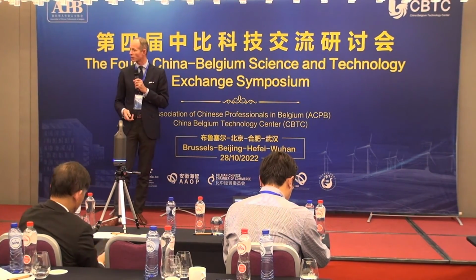Depending on the concentration of CO2, it will increase the process or not. And actually, this is identified as a drawback of concrete, because if the front of carbonation is going too close to the steel reinforcement, you will have a problem. But at the end of the day, this carbonation on all existing concrete structures worldwide becomes significant.